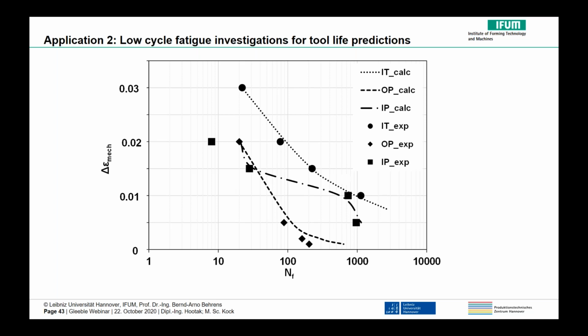The LCF tests have shown that the room temperature strain life curve can be considered an upper bound on life. In the TMF tests, the achieved cycles of all test specimens were found to be less than those during room temperature tests. Any decrease in life can be attributed to oxidation effects, creep effects, or both. The total strain amplitude versus cycles until crack curves are illustrated in the figure for the three cases of isothermal LCF tests, thermo-mechanical OP, as well as IP tests.